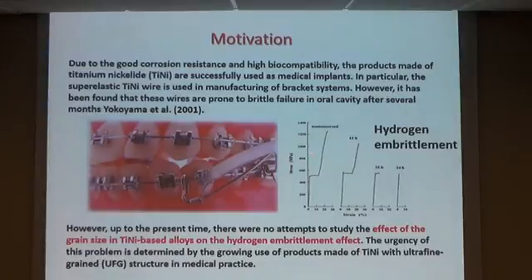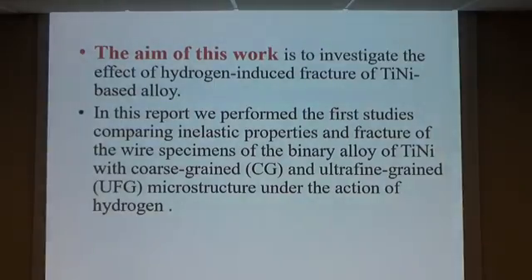However, up to the present time, there were no attempts to study the effect of grain size in titanium nickelide-based alloys on the hydrogen embrittlement effect. This work is to investigate the effect of hydrogen-induced fracture of titanium nickelide-based alloy. In this report, we performed first studies comparing inelastic properties and fracture of wire specimens of binary titanium nickelide alloy with coarse grain and ultrafine grain microstructure under the action of hydrogen.